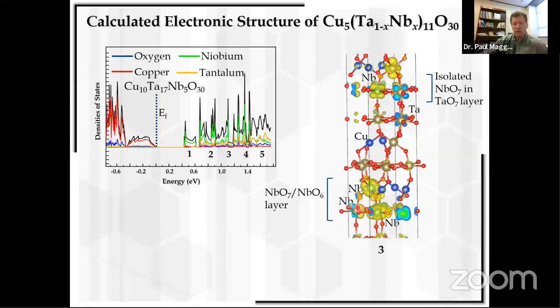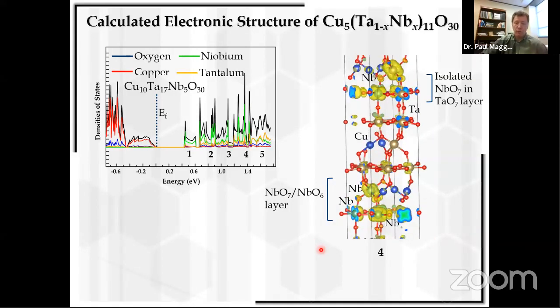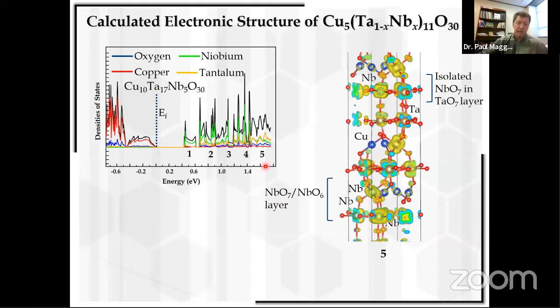We go to 3, right? Here's the electron density from region 3 in the conduction band. And now you see the electron density is spread out more over both the isolated niobium as well as the extended niobate part of that network. And then 4 and then 5. And by the time we get up to this high energy of the conduction band, the electron density is spread out over that entire network, such that when light excites an electron from the valence band to the conduction band, because there's multiple wavelengths coming in, electrons are being excited from high energies to low energies in that conduction band.